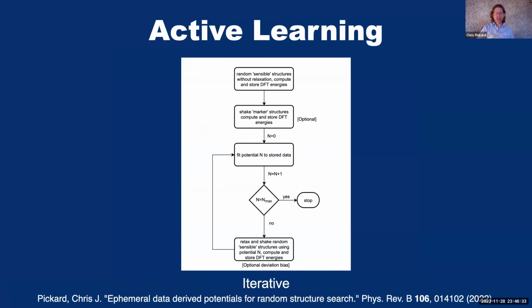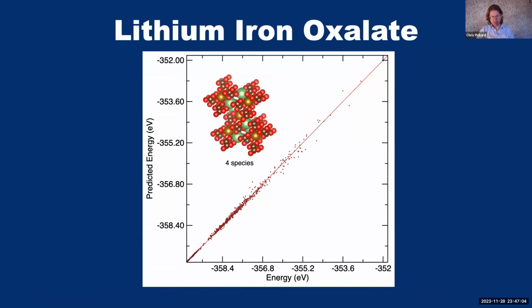So our active learning scheme is starting with completely random structures that we calculate the density functional theory energies of. We can add some marker structures. You don't have to, but marker structures are structures that we know should exist in the energy landscape. And then we go around a loop where we make a potential from the data set that we have, do some random structure searching with that potential, and then add that data back into the data set. And it iteratively improves the potential.